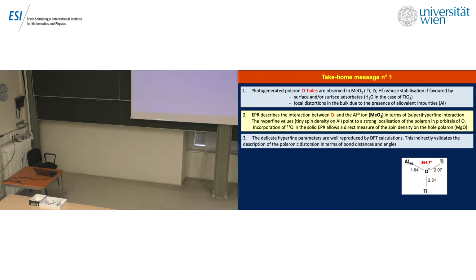Well, this is the first take-home message. Photo-generated polaron holes are observed in all these systems. The EPR describes the interaction between the oxygen and the aluminium ion nearby, when you have oxygen 17 in the system, as I've shown. The delicate hyperfine parameters are well reproduced by DFT calculation, and this indirectly validates the description of the polaronic distortion, in my opinion.